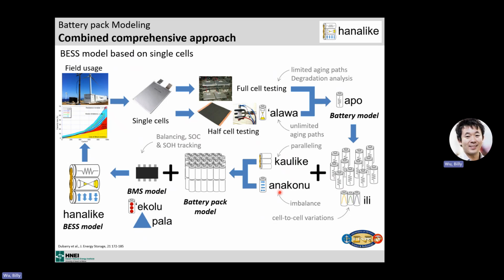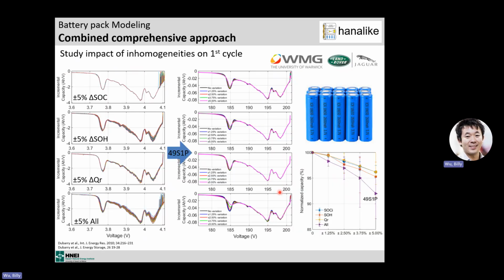We can simulate possible degradation in any cell. We can change the level of cell separation, track any imbalance if we need to, and we can control it in different ways. That's an example of some work we did with Warwick years ago on the impact of inhomogeneities on the first cycle. We look at the impact of imbalance in SOC inhomogeneities, SOH inhomogeneities, and capacity inhomogeneities, all at the same time. And we did that for different pack configurations, from all in series to all in parallel, and a mix of both.